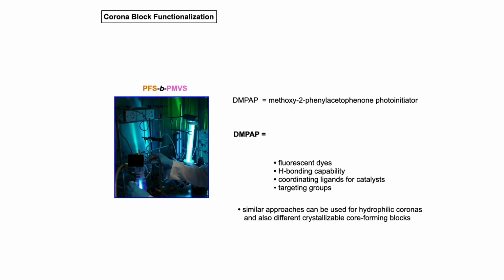You can take these molecules, called thiols, and buy an enormous variety of these structures. If you add light, shining it on the solution in the presence of this photoinitiator, you get a photoreaction where the thiol adds to the vinyl group and tags it on there. This is incredibly useful because it means you can functionalize the corona forming block with anything you like. This enables you to make fiber-like micelles where any functionality you want is expressed on the surface of the corona, and we use this for an enormous number of applications.